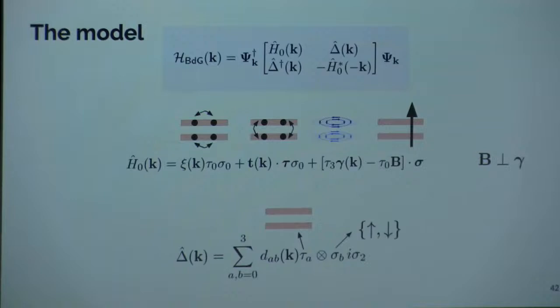This is a BDG Hamiltonian. The first term has the intra-layer hoppings. The second term is the inter-layer hoppings. I could use either Ising or Rashba spin-orbit coupling. I will talk about Rashba spin-orbit coupling, but everything is applicable to the Ising case as well. So here I have Rashba, and the last term is a perpendicular magnetic field. And here I am looking at the case where the magnetic field is perpendicular to the spin-orbit texture.